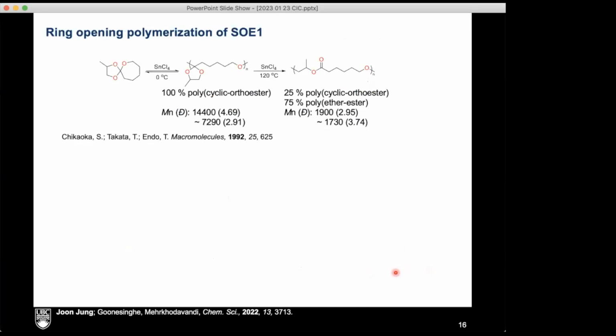And we know that we can polymerize them. There are these really interesting examples of expanding monomers. So usually when you have a monomer and you polymerize it, the final product shrinks, right? Because if you think about monomer molecules, there's a lot of space beside them, and then if you polymerize them, they get closer together. So the whole volume of the material will shrink. In this case, these are polymers that, because the monomer is actually expanding, the polymer expands, so they have some